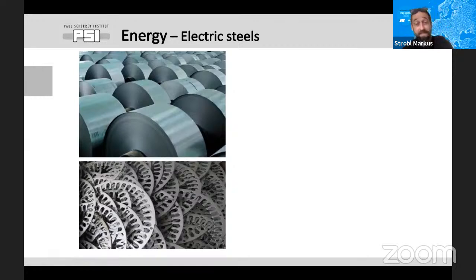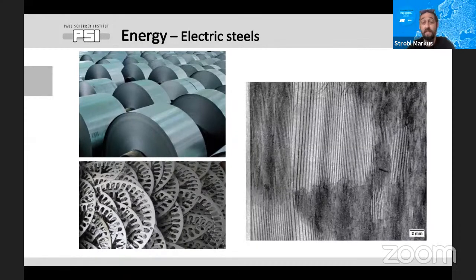And why I like this example, because this uses a relatively newly developed method that we developed also in particular here at PSI, grating interferometry, which enabled us to see the magnetic domain walls in such materials, even if they are coated, which they need to be for the machinery. And we can very well characterize the magnetic domain structure.